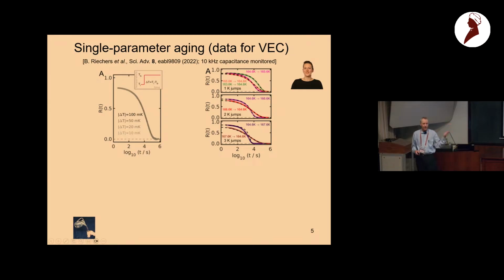But from that, we can calculate the nonlinear ones from the equations I showed you previously. It doesn't have to be two nonlinear. One can be linear, one can be nonlinear. So the predictions are given by the dashed curves here for 1, 2, and 3 Kelvin jumps. There's some deviation here, which Christine speculates may actually be an error of ours. But anyway, it works pretty well, predicting the nonlinear jumps.